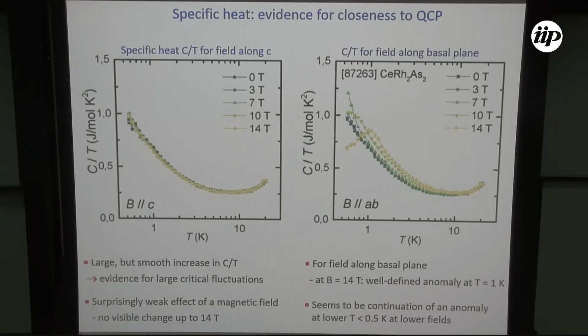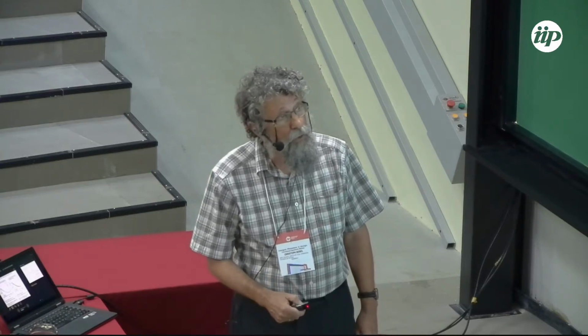What is very surprising is that you apply 14 Tesla and you do not see any change. The change is so small that when we showed this curve to our low temperature experts, they said, okay, you just forgot to put on the magnetic field. But later it was shown that indeed there is no change along this direction for a field of 14 Tesla. In the basal plane, we also observed a pretty small change, but then at the highest field we see a peak here, which indicates some transition.